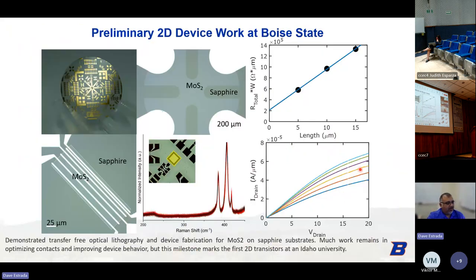Nonetheless, we are moving towards devices with these films, working with Aixtron. This is just an example where we've developed a contact photolithography method where we can do this directly on transparent substrates, so we don't have to transfer our films off sapphire. You can see the MoS2 film pattern directly on sapphire here. We also have TLM structures on this wafer, so we can look at contact resistance and transfer length.